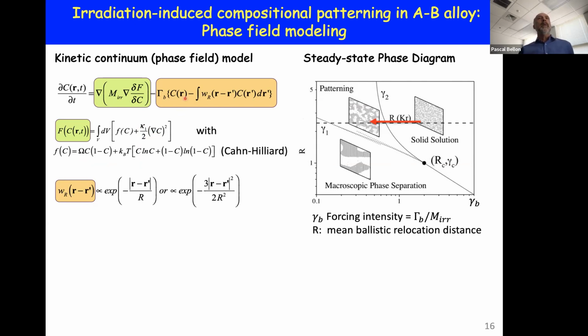For the mixing, since the mixing takes place over a range of distances, we have to use a different model. And here we describe the mixing as a convolution product. Essentially, we're just saying the concentration at site R decreases because we relocate this atom B elsewhere at a frequency gamma B, and atoms that were sitting at a site R prime may be relocated to site R through that same process, but this is weighted by a distribution function for these relocation distances. And we have reasons, from MD simulations, to use either exponential or Gaussian relocation distribution functions. And so I'm going to use a Gaussian form for simplicity in the next few slides.